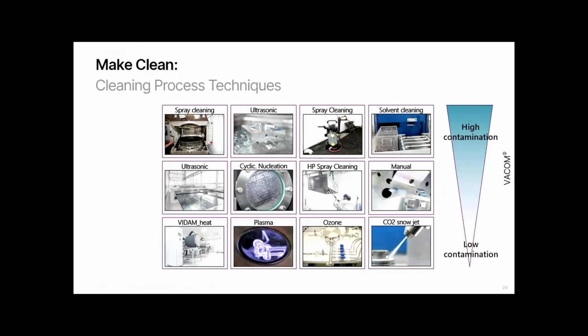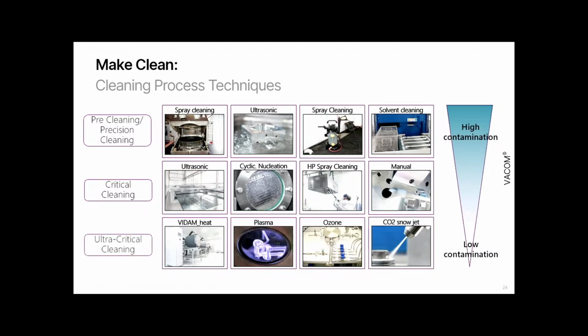So when you talk about making a part clean, you have different techniques that can be used depending on the contamination level of the parts and the intended cleaning specification, right? So if a part comes in that is highly contaminated, we need pre-cleaning, maybe a spray cleaning, ultrasonic baths, or solvent cleaning in order to get rid of that initial contamination. Then after that, we move on to critical cleaning that can be done through ultrasonics again, or cavitation, high pressure spray cleaning, or even manual cleaning steps as well. And then if you go into the ultra critical cleaning, that's where you need vacuum bakeout. You use maybe plasma treatments, ozone or CO2 snow jets to really get rid of the last bit of contamination. So basically, it's an exponential curve. The effort increases and increases, and the contamination that you get rid of is smaller and smaller.